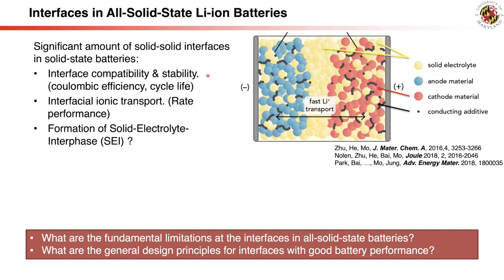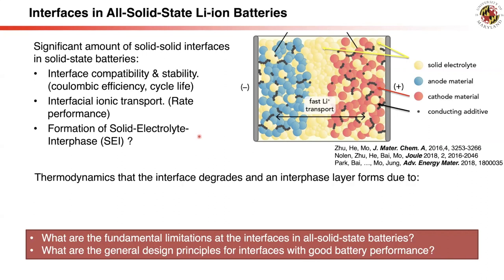Interface compatibility and stability is crucial in affecting battery performance, such as the charging-discharging rate, coulombic efficiency, and cycle life. The formation of a solid-electrolyte interphase (SEI) layer in solid-state battery is also a critical question. To understand these interfaces, thermodynamics can be used to evaluate reactions such as interface degradation and the formation of an interphase layer.